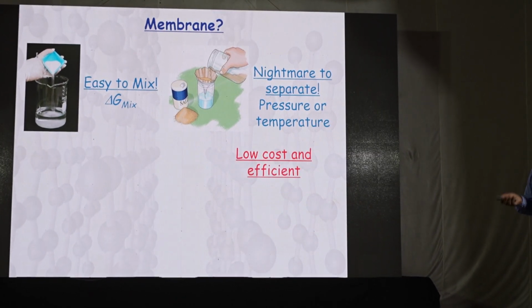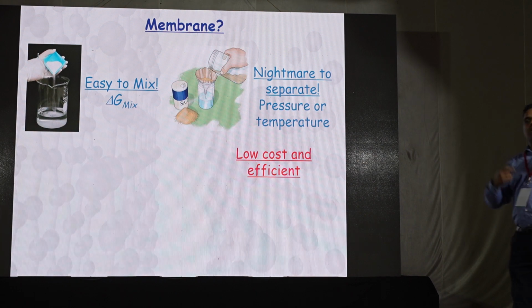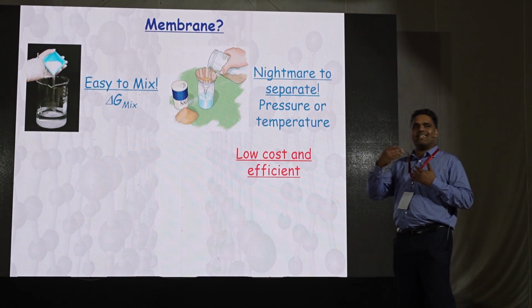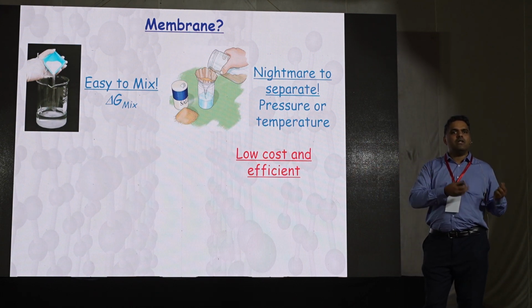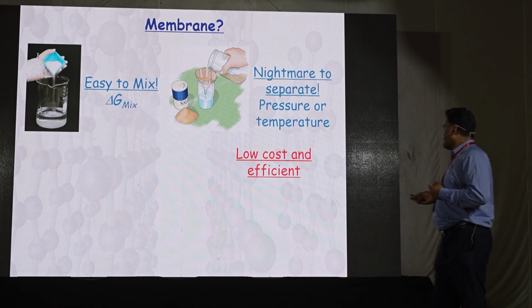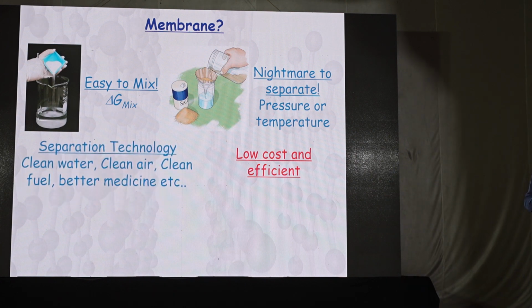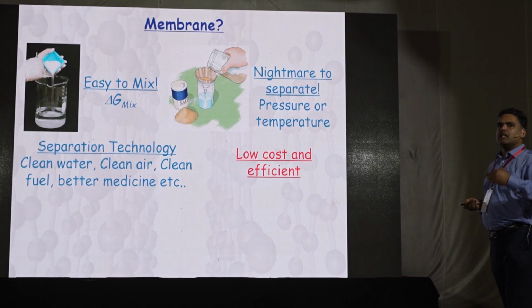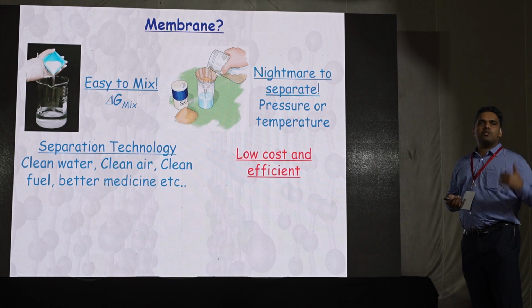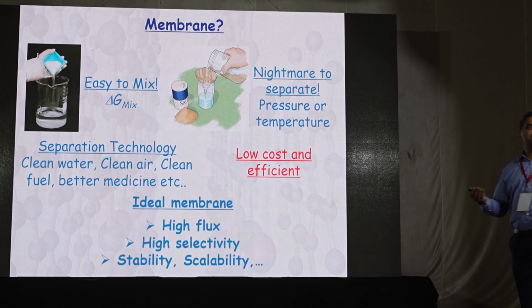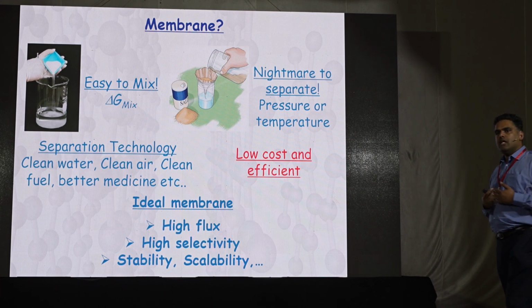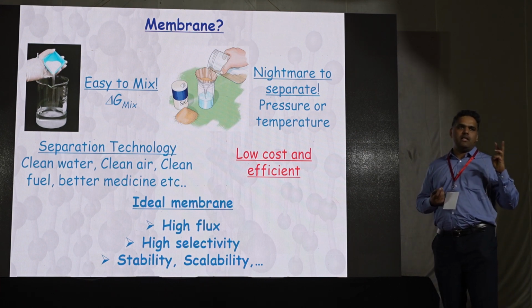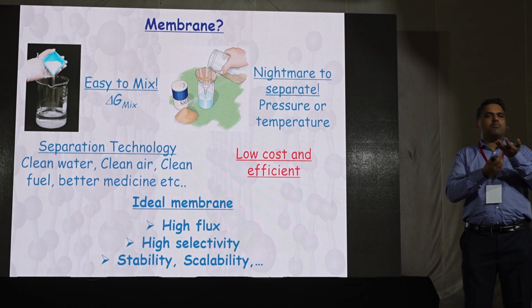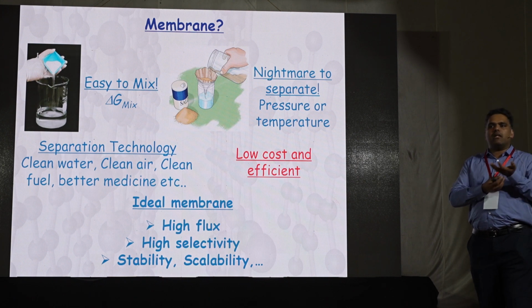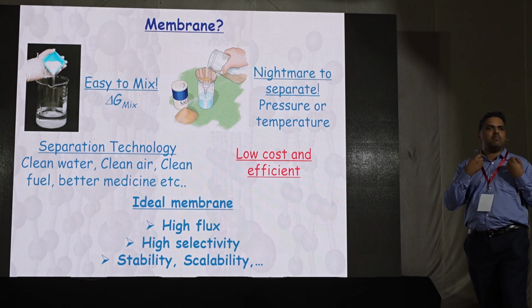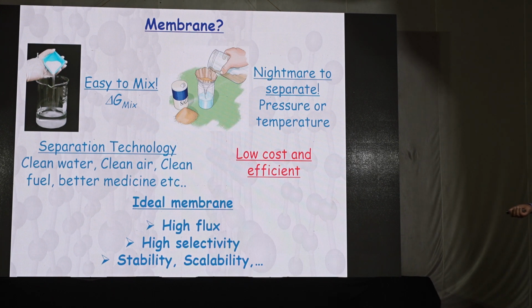So if you want to separate, either you have to heat it up or you can apply a pressure. It's called osmotic pressure. You have to apply a pressure greater than the osmotic pressure to separate salt from water, or any molecule or any solvent from another solvent. That is why membranes are important. Membranes are selective. They can selectively pass one molecule and block the other one. But again, you have to overcome the osmotic pressure to separate it. So to make an energy efficient separation process, you have to design a membrane which gives high flow rate. Imagine you have a membrane and water is coming drop by drop, it is not efficient. But if you can get 1 cup of water within a second, that process will be much more efficient. So an ideal membrane will be a membrane with high flux.